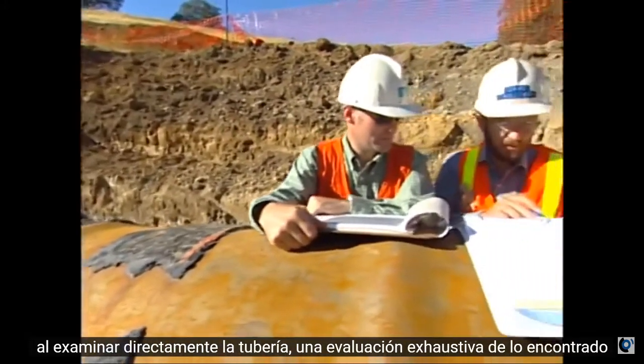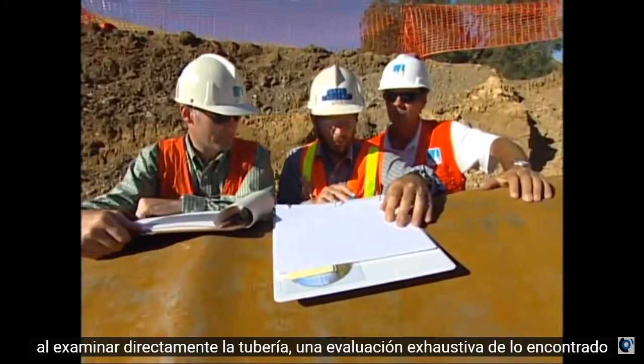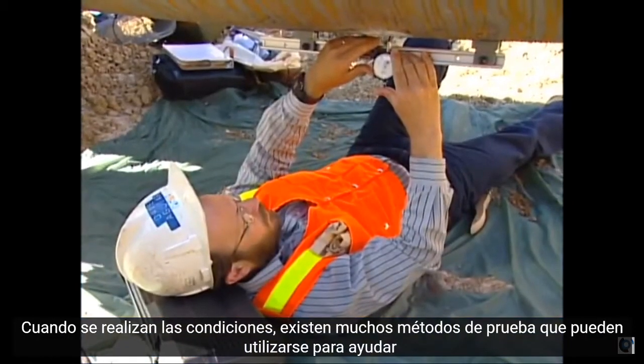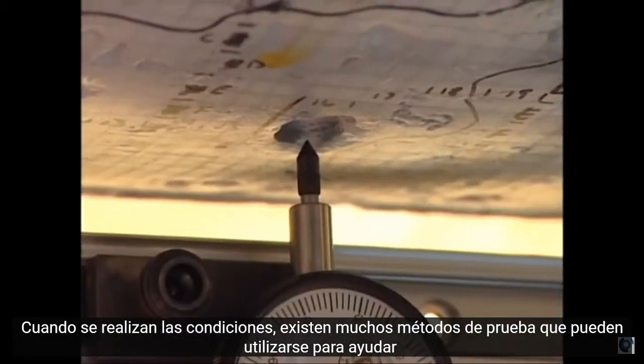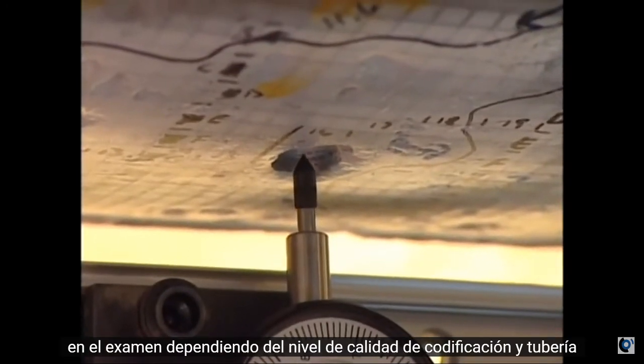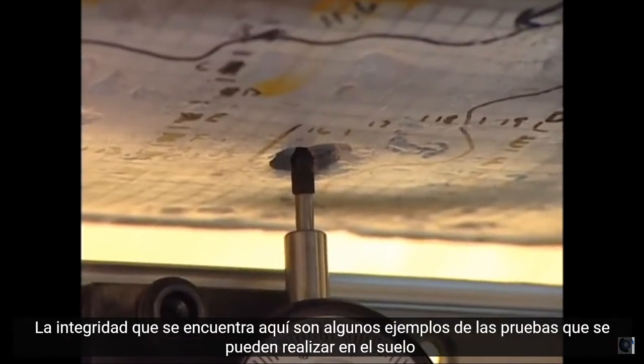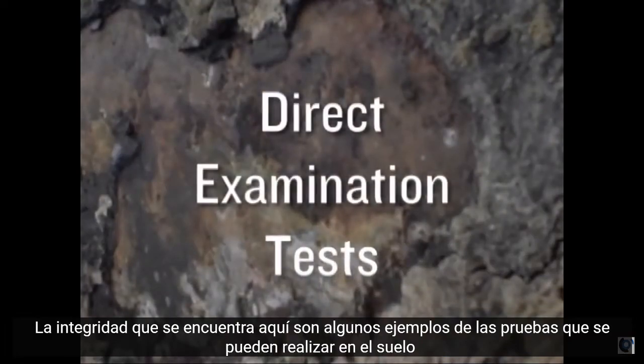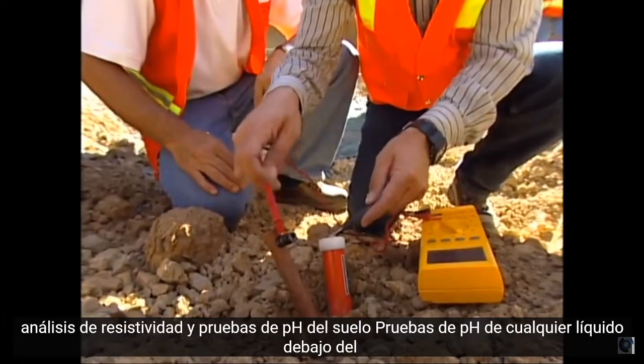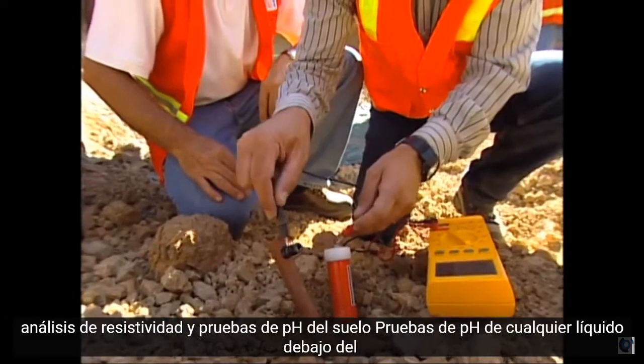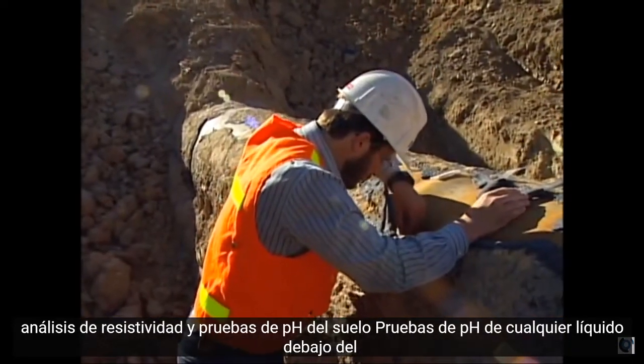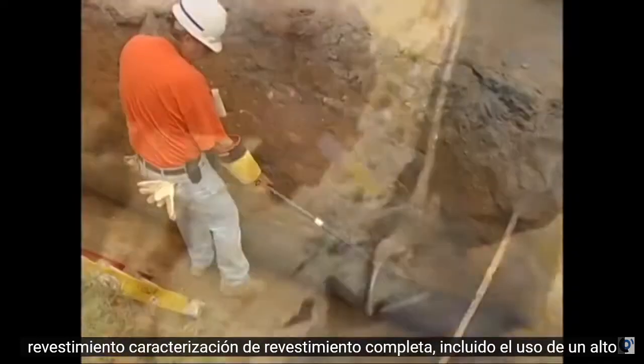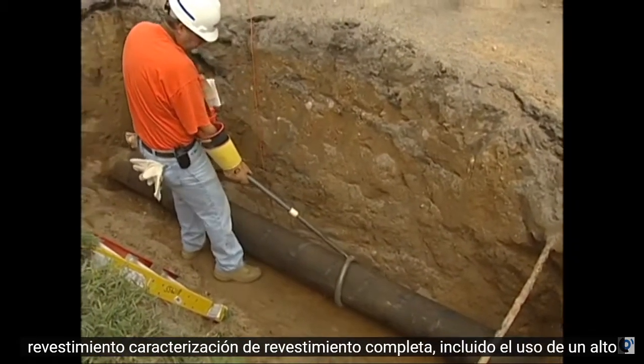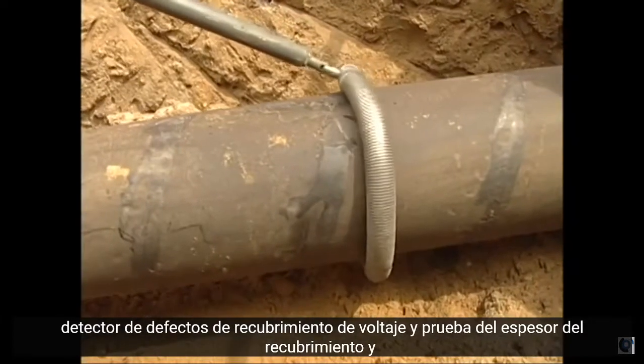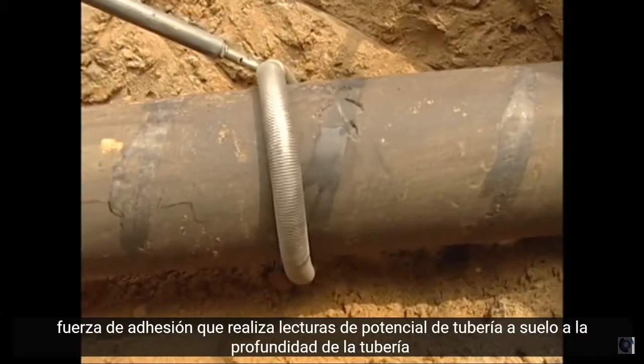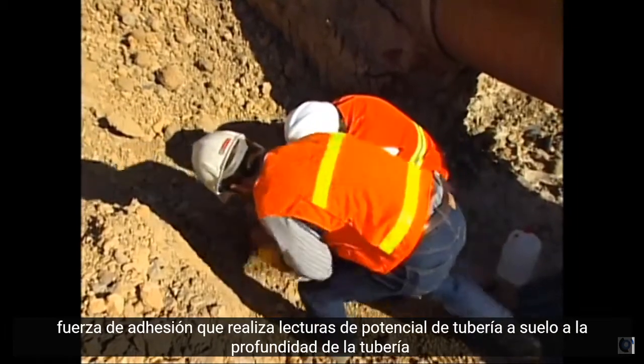When directly examining the pipe, a comprehensive evaluation of the as-found conditions is performed. There are many test methods that can be used to assist in the examination, depending on the level of coating quality and pipe integrity found. Here are some examples of the tests that can be performed: soil analysis, resistivity, and soil pH testing, pH testing of any liquid underneath the coating, complete coating characterization, including using a high-voltage coating flaw detector and testing the coating thickness and adhesion strength, performing pipe-to-soil potential reads at the pipe depth,